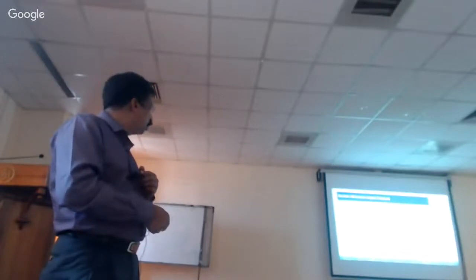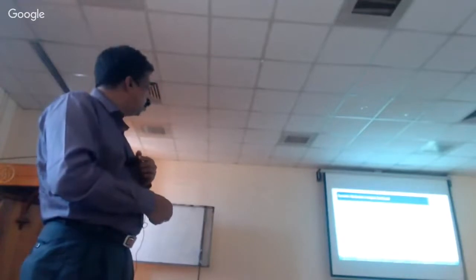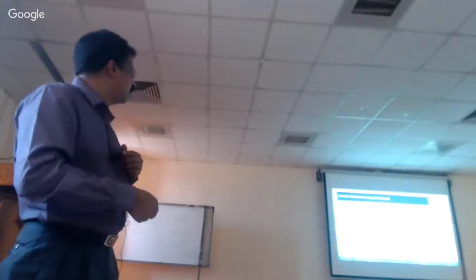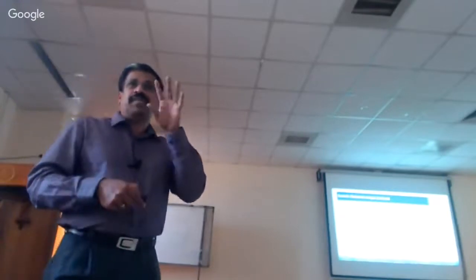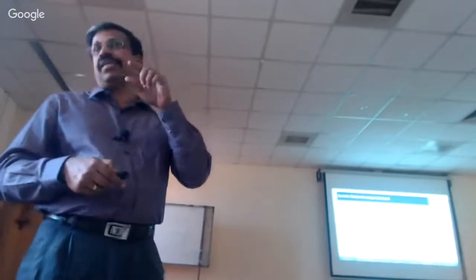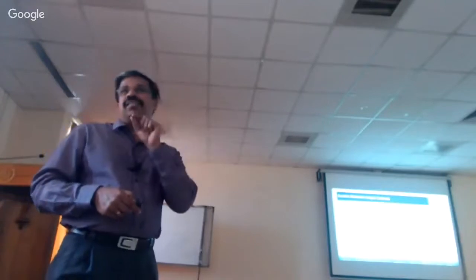See, here you get two moduli. One is the storage modulus, and the other is the loss modulus. This is the loss modulus. So when we apply a sinusoidal stress and strain, we get the viscoelastic properties